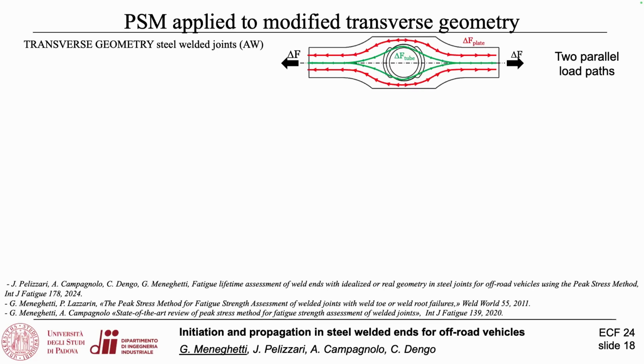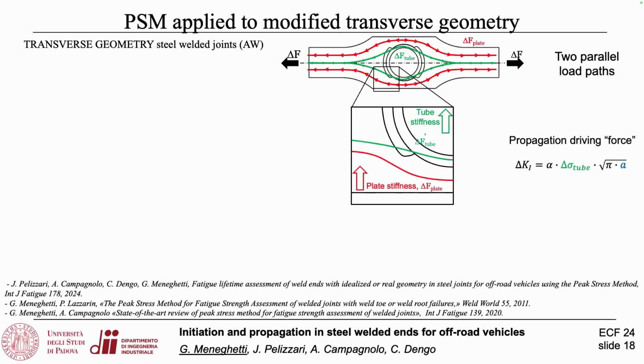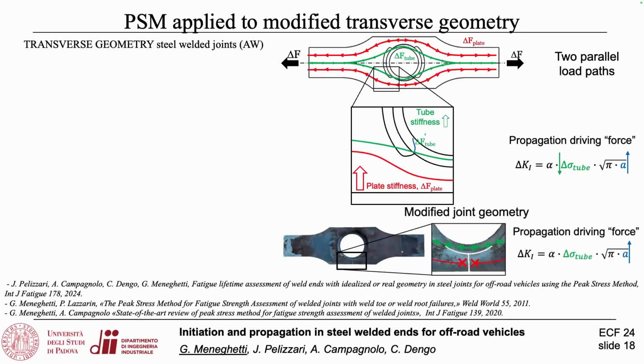If you consider the stress flow coming to the welded joints, the stress flow can follow the net section in the plate or can engage the weld seams and enter the tube. Now, when the crack initiates at the tube, the stiffness of the tube decreases while the stiffness of the plate is the same. So in the course of the fatigue test, we have a decreasing stress flow engaging the weld, even though the crack length increases. So the resulting stress intensity factor is more or less constant. We have proved that with dedicated calculations.